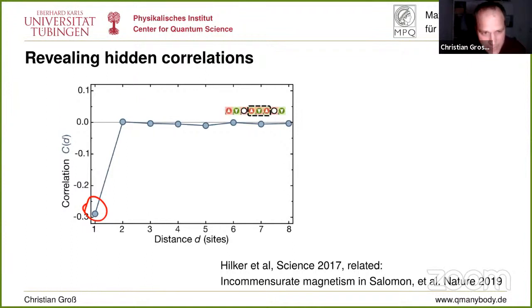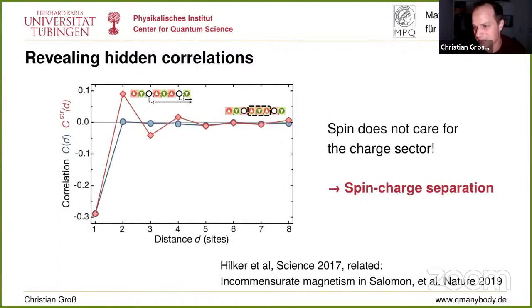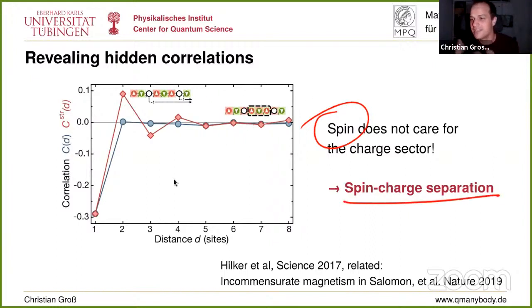And let's analyze the same system with the string correlator. And you see we are getting the same tic-tac behavior back that we had before with the fully filled systems without holes. We could really put them on top of each other, and you will see that the curves are basically indistinguishable. And that shows you that really the spin, if I analyze it with the right observable, doesn't care that I have holes in the system. And this is kind of an incarnation, measured with a weird multi-point correlator, of spin charge separation that we measure here neither in the spectral quantity nor by some dynamics, but just by analyzing fancy correlators in that system that are enabled by quantum gas microscopy.